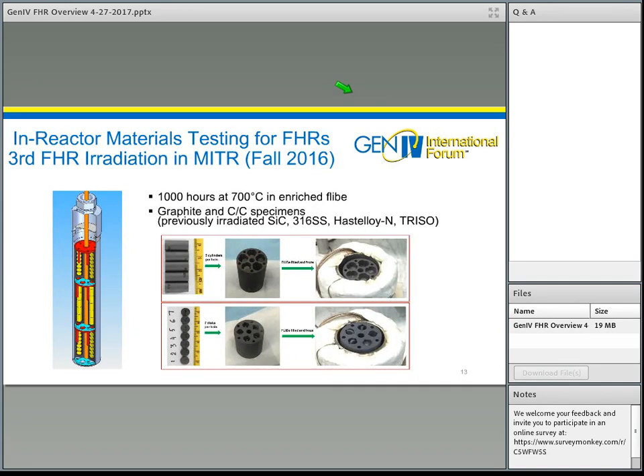At MIT, there's been a series of irradiation experiments with FLiBe and structural materials placed in the MIT reactor to study corrosion. And these experiments have also been successful in allowing us to study the generation, transport, and fate of tritium. Tritium is one of the key technical issues one faces with FHRs. Quantities of tritium that are produced in FHRs are significantly larger than in pressurized water reactors. They're closer to the quantities that are produced in heavy water reactors, and therefore there's sufficiently large amounts that it is necessary to control tritium and to recover the majority of the tritium from the reactors, as is done with heavy water reactors like the CANDUs.